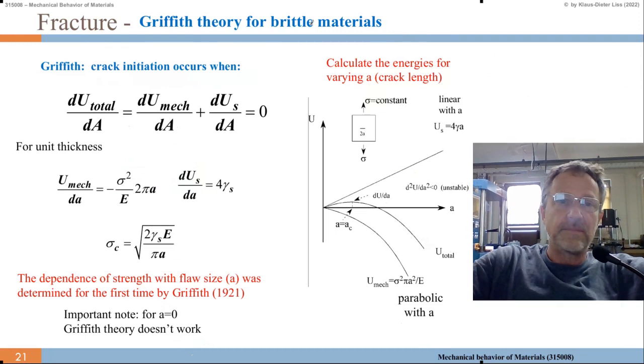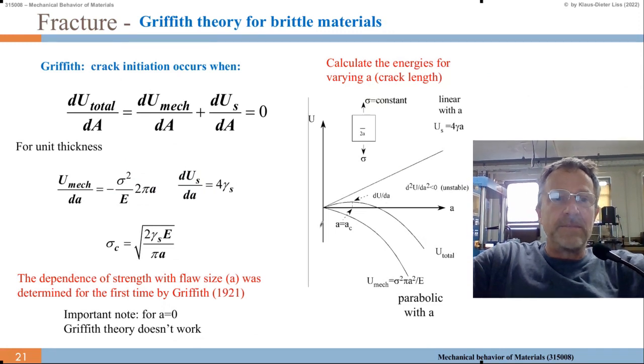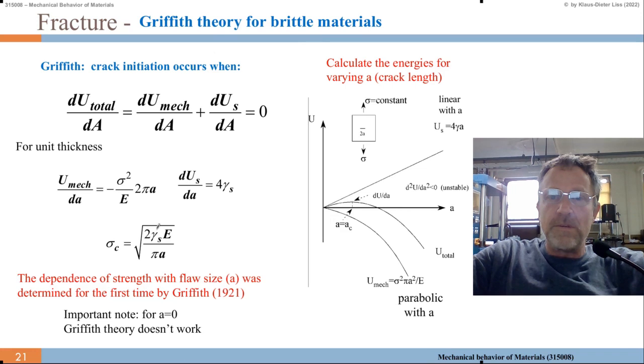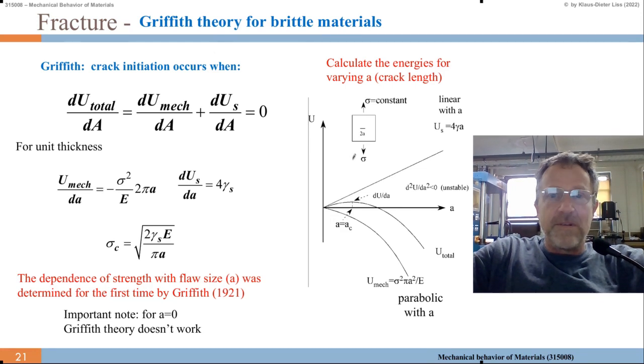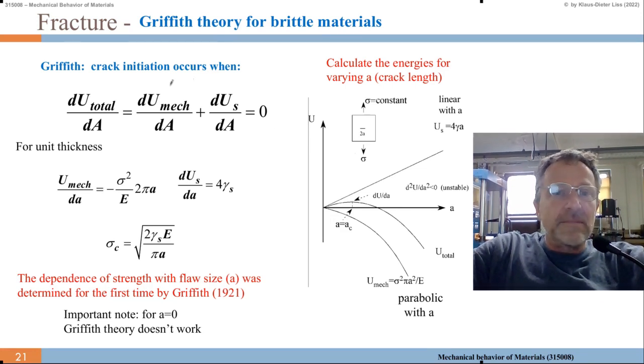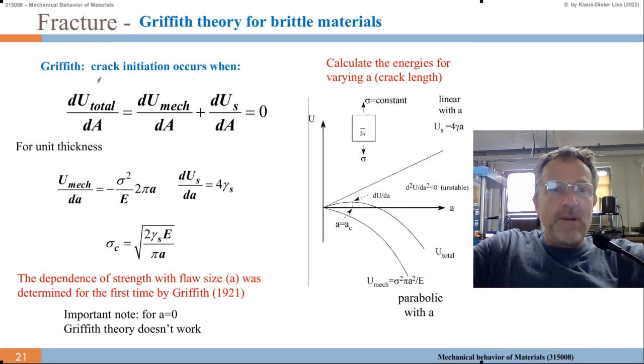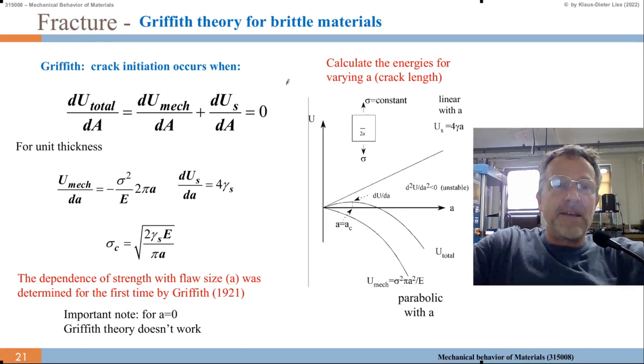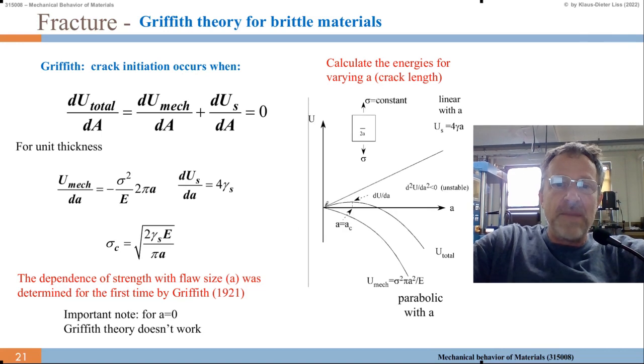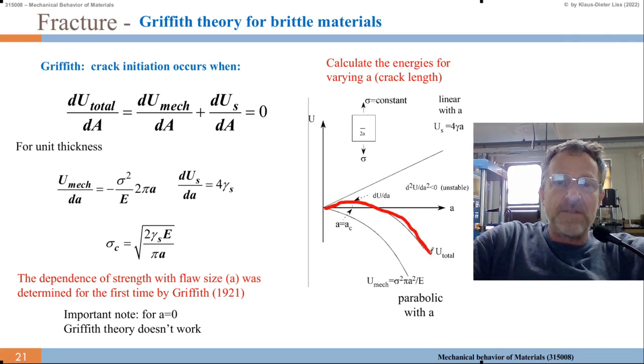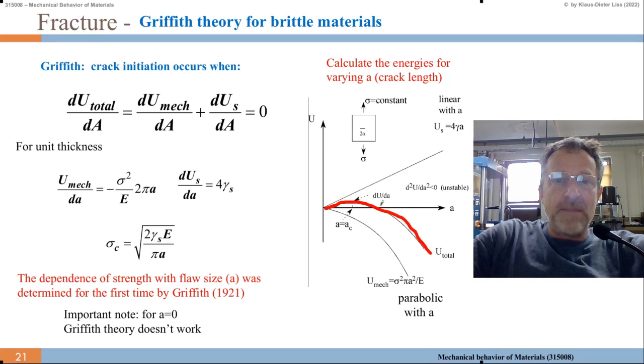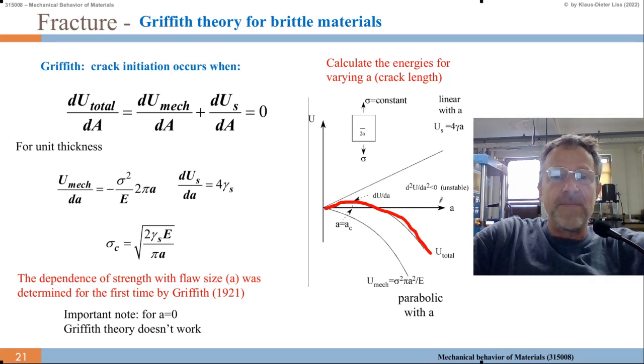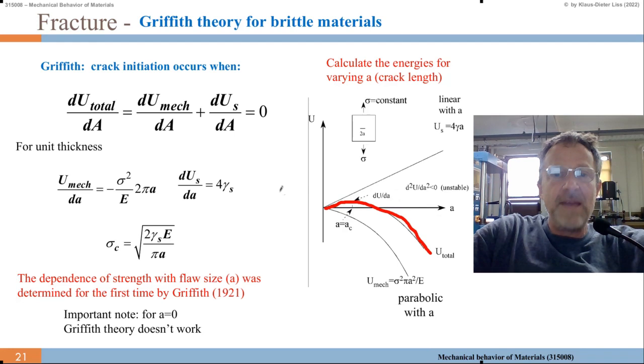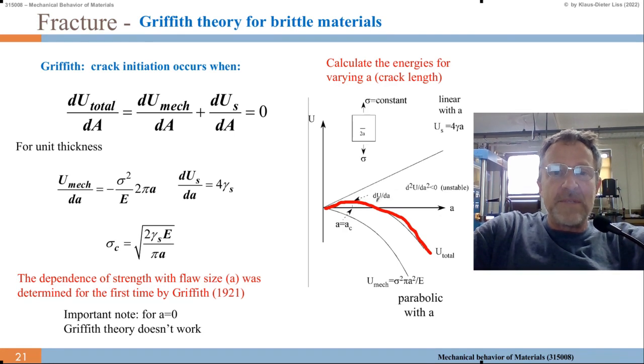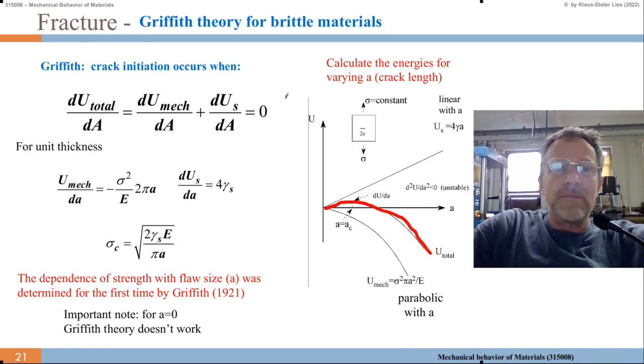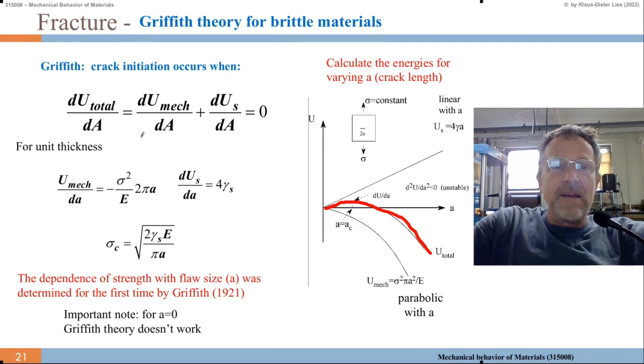So now we look to these different energies. We have the mechanical energy, and we look to the change of energy. So crack initiation occurs when, basically, we have this function here. We have such a function which has a maximum, and dU over dA, as a function of crack length A, if it becomes horizontal, so the derivative becomes 0, then I get crack initiation.